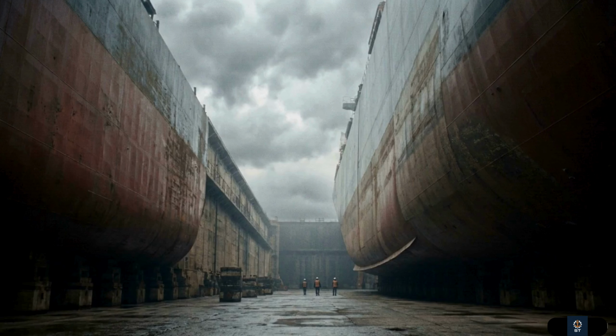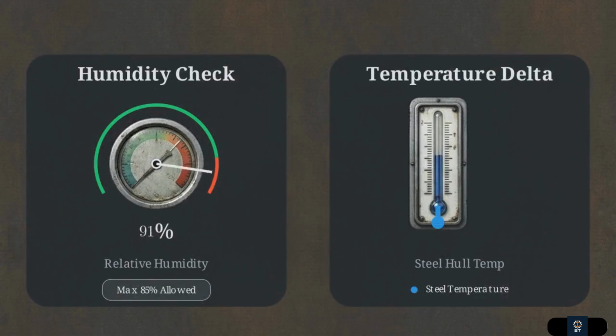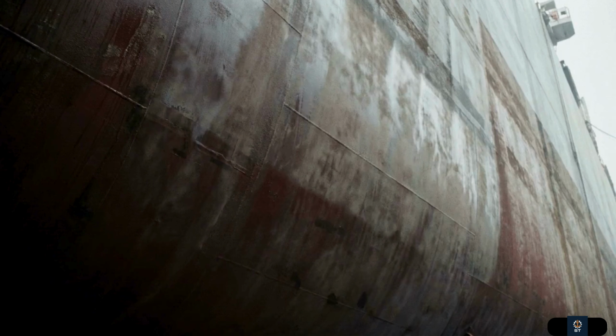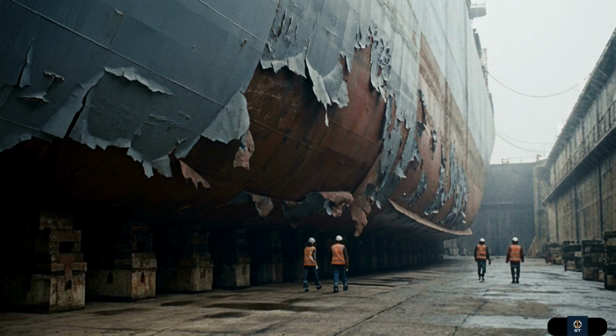This advanced chemistry is entirely at the mercy of the weather. Application requires relative humidity to be below 85% and the steel temperature to remain at least 3 degrees above the dew point to prevent condensation. If applied in high humidity, epoxy coatings can develop amine blush, an invisible waxy film. This blush destroys the adhesion of any subsequent layer, condemning a multi-million-dollar paint job to premature failure.